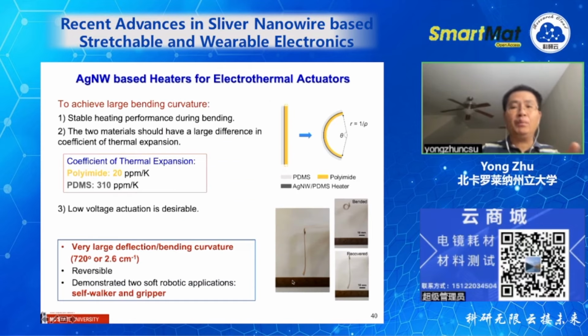And then we bond these materials with another material with a very different thermal expansion coefficient. In this case, we use polyimide. Polyimide's thermal expansion coefficient is very small, only 20, compared to the PDMS, which is 310. So you have a large difference in thermal expansion coefficient, and this is the so-called thermal bimorph, right?